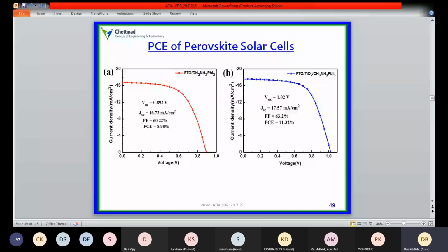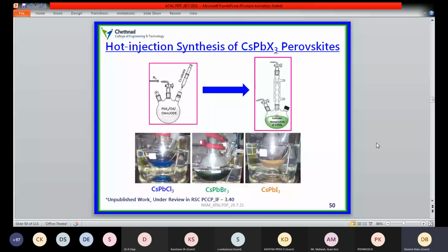And this is our second work, where we have used the hot injection synthesis methodology to prepare cesium lead halide perovskite systems. So under an inert atmosphere, we have used lead halide systems, oleic acid, oleylamine, and octadecene solvents in the presence of nitrogen atmosphere. And we have prepared these three systems: cesium lead chloride, bromide, and iodide systems. And the characterization for the cesium lead bromide system is shown here,